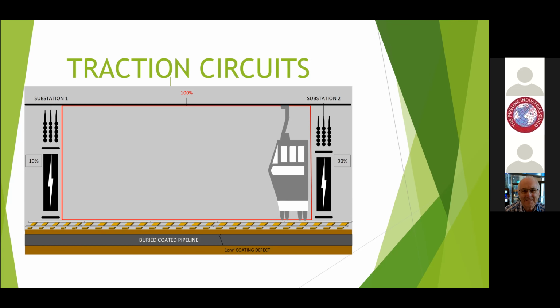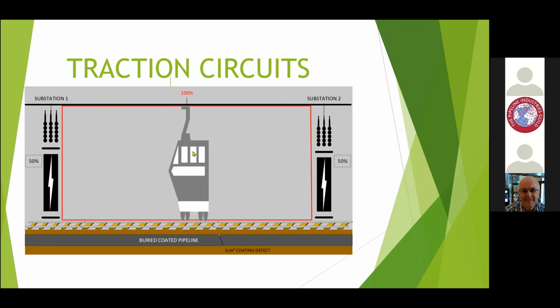But on this 1 centimeter square coating defect here, you can see that it's subject to the interference of the electric current that's flowing through the track and the overhead power line, because each of them has a magnetic field. It's subject to that while the train is there. And when the train's near this substation and going in that direction, it takes about 90% of its current from here and 10% from there. Then as it moves along to the middle of the track, it's taking 50% from this one and 50% from that one. And then, as you'd expect, when it gets up to this one, it takes 90% from there.